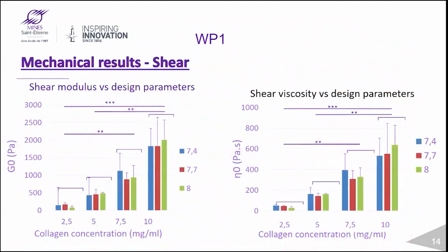We measured the mechanical properties of the hydrogels, and we found results consistent with the literature, so a proportional increase in modulus and viscosity with the collagen concentration only.